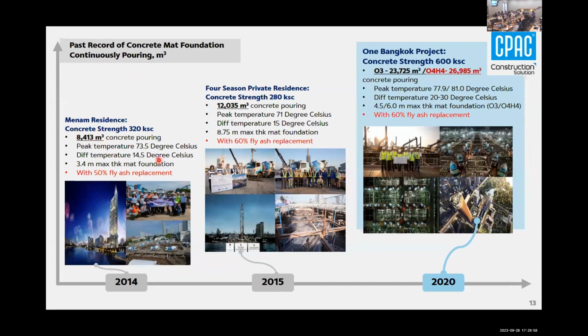The first one has a volume of around 8,000 cubic meters with the strength here. We replaced with fly ash around 50%. You can see the temperature numbers here and the thickness of the structure. The first one, Menam Residence, is around 3.4 meters. The next one is more challenging, but the strength is not higher, it's almost the same. Sorry, this one is 280 ksc, around 28 MPa, and the volume of concrete becomes higher, 12,000 cubic meters, continuous pouring, but the strength is not high, so it's not much of an issue.